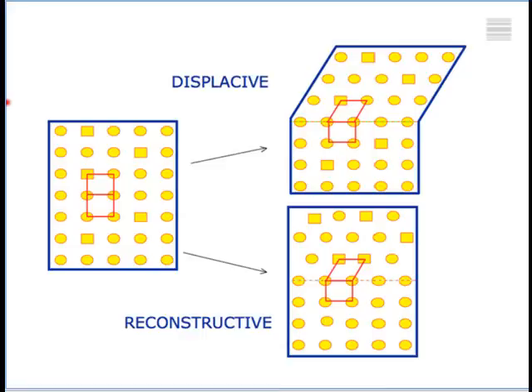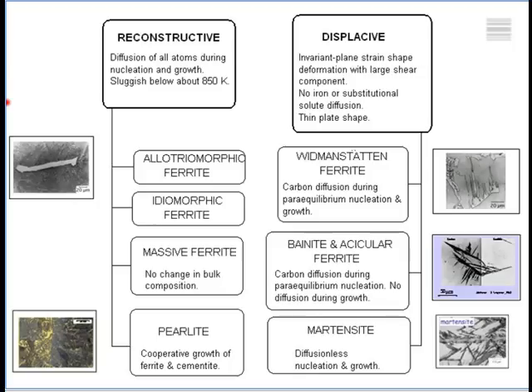Now, to summarize the key structures that occur in steels, I've got a diagram here with a little bit of detail, but you don't need to worry about the detail. You can see the two classifications, displacive transformations and reconstructive transformations. Displacive transformations, martensite is the most obvious that most people are familiar with. You simply quench the steel to obtain martensite. You have bainite and acicular ferrite, Widmanstätten ferrite. And in the case of the reconstructive transformations, which require diffusion to occur, we have pearlite and ferrite, or allotriomorphic ferrite.